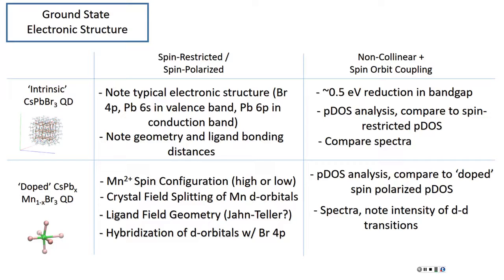Okay, so you already checked it. I've started to; I may have to redo some of them, but I do see again the orbital ordering, and it's pretty consistent with what you'd expect for the symmetry. But then maybe, just illustrative, put it in your figure: if you show this kind of structure, you probably can also show your splitting in levels as it is expected from the symmetry.